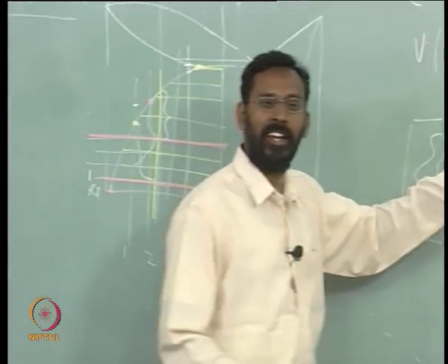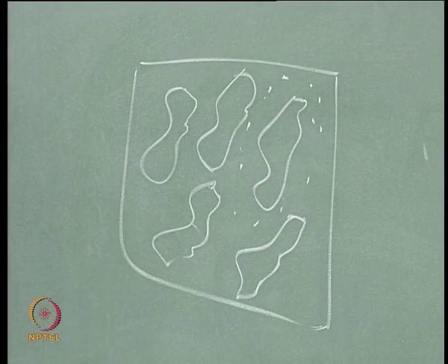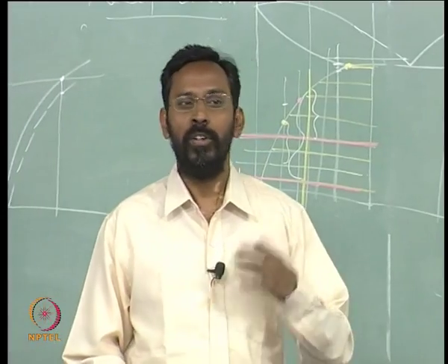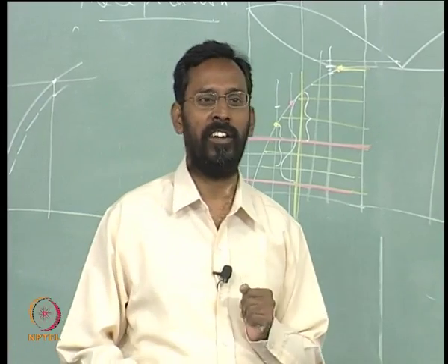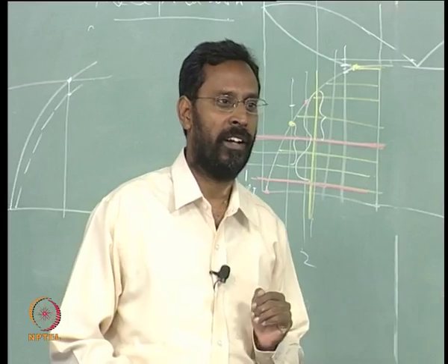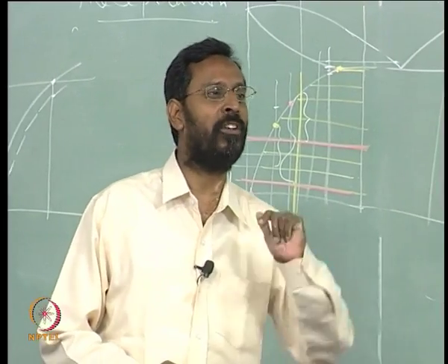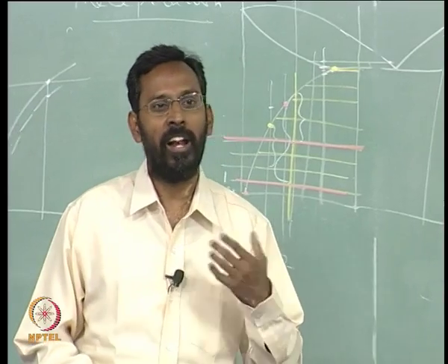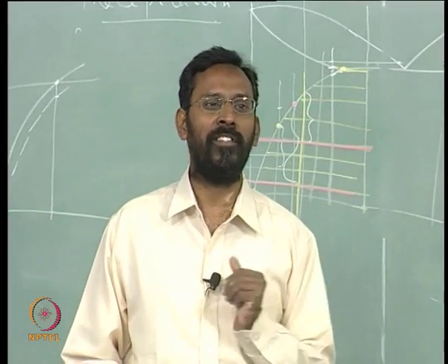So that is easy to understand on a hypo. On the hyper, we already know it is the theta that has already come out. So you can say the theta of the eutectic mixture nucleates on the theta which is already existing. But if you are at exactly the eutectic composition, it is very difficult to say. That is where people say the phase which is easier to nucleate, which has a lower activation barrier, whose structure is similar to that of the liquid structure,